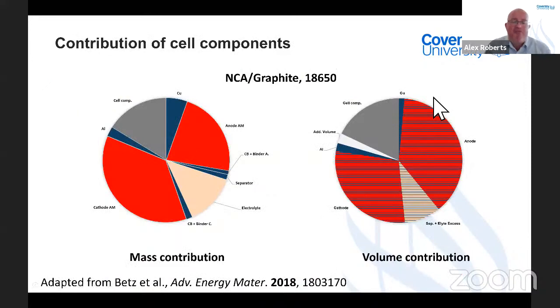If we take some excellent work looking at these cell components and the contribution of components, take an example of an NCA graphite 18650 cylindrical cell and break that down at the manufactured level, we can see there is still a significant amount of the cell mass and volume coming from the anode and cathode active materials, but we've got a large proportion that's coming from other components in there.